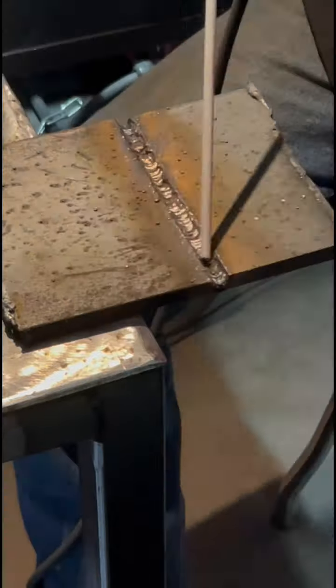But this one here, I do the tacking method. I just brush it down instead of grinding it down like you're supposed to, and then I just run a big old 7018 weave just to cover everything up. Really, this is not the best method to do it because it overheats the material and can cause some brittleness and some cracking, along with a lot of porosity.